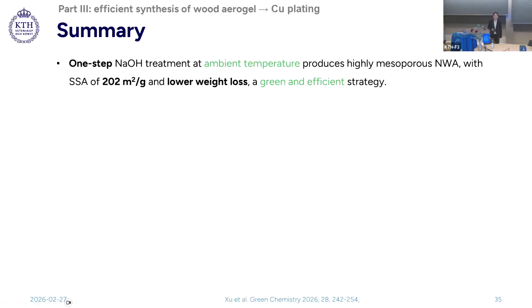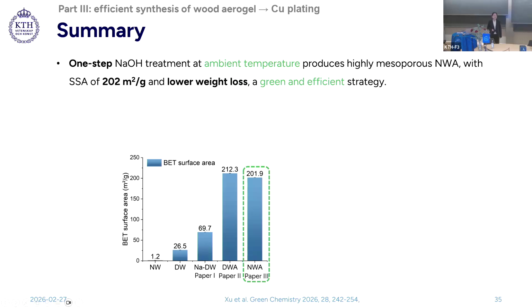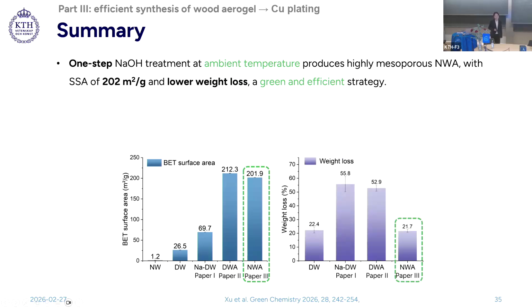In summary, here, a one-step sodium hydroxide treatment at ambient temperature was developed to produce highly mesoporous wood aerogel. The resulting specific surface area is comparable with the values reported in paper 2, but with a significantly lower weight loss, indicating it is a green and efficient cell wall engineering strategy.